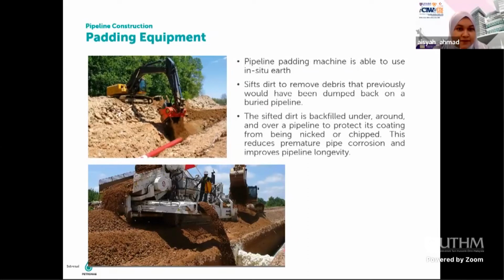So this is a padding equipment, something that we use to remove dirt or debris. As you can see in the picture, it sieves the dirt to remove debris that previously would have been dumped back into the buried pipeline. So we use this padding equipment to sieve the dirt and backfill under, around and over a pipeline, in order to protect the pipeline coating from being nicked or chipped. As I mentioned, this is a common theme throughout the pipeline installation. Okay, next please.